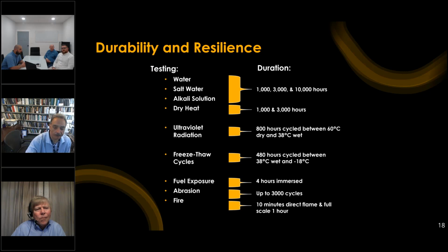The samples are inside of a UVA chamber with direct UVA exposure, and they're held off of the light only a few inches. And it is difficult in some regards to correlate testing within a lab environment to field performance. But certainly with ultraviolet, especially in a bridge structure, you're going to see more exposure on the upstream or downstream girders and the fascia, and you might get some reflection off of water surfaces, but the exposure in the real world is going to be lower than what's applied in the lab with this direct UVA exposure.